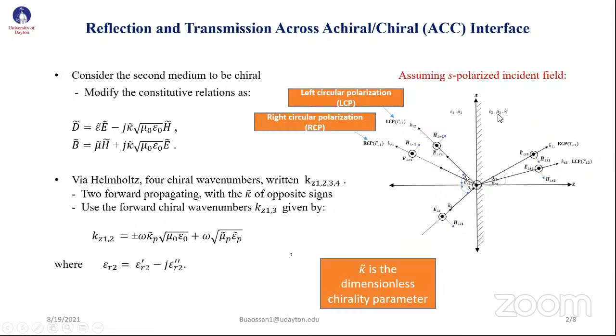So we can see here that it depends on epsilon 2, mu 2, and kappa, which is the third parameter we apply for the chiral material. Since we are speaking about chiral material, the normal constitutive relation is modified. If we make kappa equal to 0, it's back to the normal constitutive relation. For an s-polarized incident field, there are two reflected fields and two transmitted fields, with left circular and right circular polarization. The chiral material also has 4 chiral wave numbers: 2 forward and 2 backward.